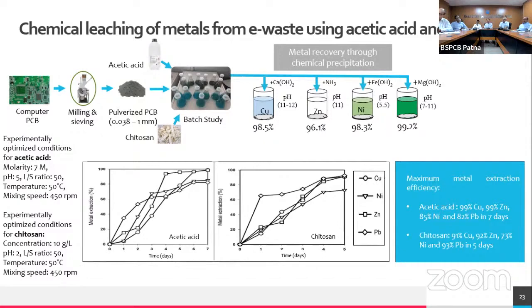So what we have got using acetic acid, as you can see, is 99% of copper, 99% of zinc, 85% of nickel, 82% of lead. The only problem is the 7 days time requirement. Using chitosan, you can see a similar kind of efficiency, but the time requirement is 5 days. Followed by this extraction from the printed circuit board solid matrices, again we have recovered the metals using chemical precipitation. The recovery is pretty high, as you can see, more than 95% for all the targeted metals.